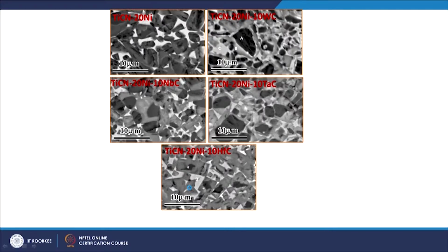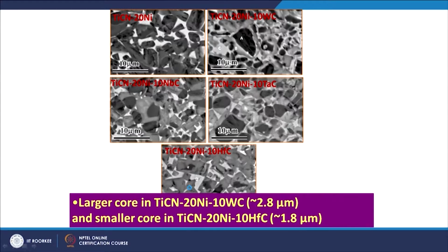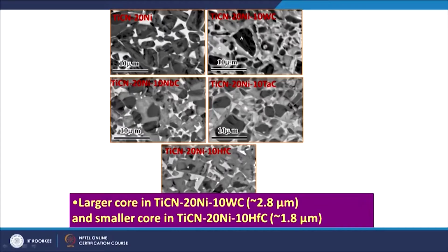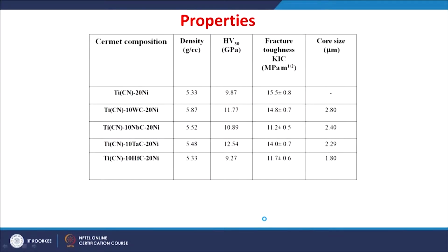So, this is a collection of the typical microstructures of the investigated cermets. You can see more or less similar features in the sintered materials, but there is a difference in the frequency of the core or rim phases as well as their size. A very systematic investigation using the line intercept method shows that the largest average core region is around 2.8 micrometer in the titanium carbonitride nickel tungsten carbide cermet, whereas the smallest core is in the titanium carbonitride nickel hafnium carbide cermet. So, there is an average size difference in the cores obtained after sintering. This actually reflects on the mechanical properties as well.